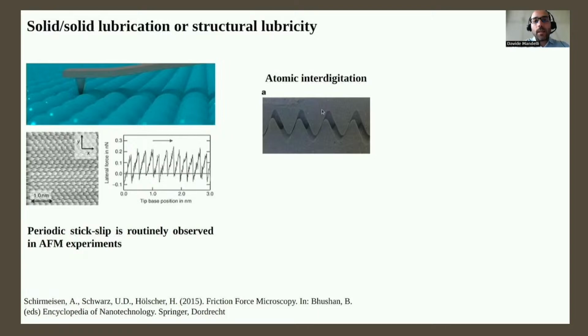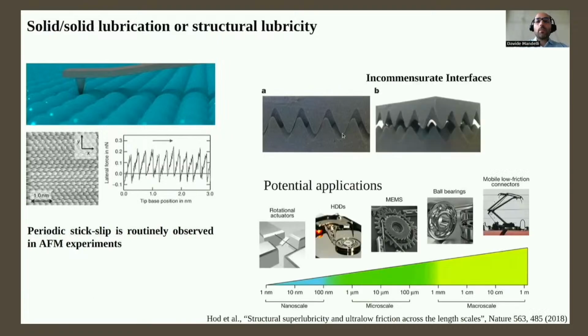So this suggests that one way of eliminating mechanical instabilities can be achieved by playing with the geometry of the interface, and in particular by building incommensurate interfaces that lead to this kind of frustrated systems where there is compensation of lateral forces, mechanical instabilities are eliminated, and one obtains a smoother and less dissipative kind of sliding. Now, studying the properties of such ideal crystalline surfaces is interesting from a fundamental point of view, but it has also potential applications, and I suggest that people interested read recent reviews like this one published in Nature a few years ago.